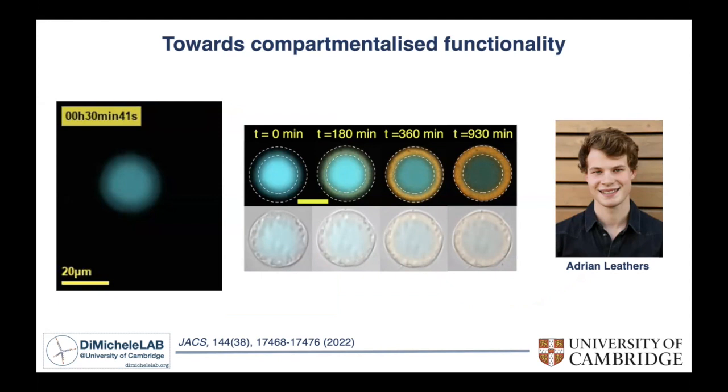Yeah, that's a great question. It's kind of hard to predict, to compare, because it's not very easy to figure out exactly how much template you have in these particular samples. But from some experiments that we have done, and they are in the SI of this paper, I think it's significantly slower compared to what you would have in the bulk.